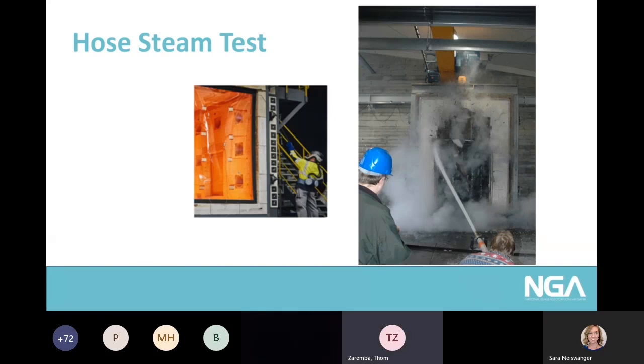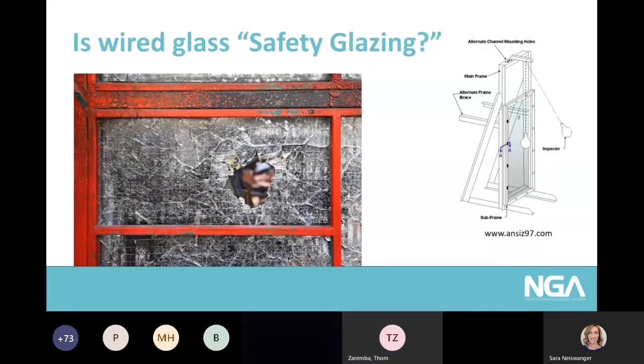Another important aspect of the use of the wire embedded in this glass is that following a 45-minute fire test, both the fire window test, NFPA 257, and the door fire test, NFPA 252, require that the glass in the door or the fire window be struck with a hose stream. And basically, there's a picture of it on the right. It resembles a fireman's hose, and it's intended to determine, after the end of the 45-minute fire test, is this product still going to remain intact when struck with the thermal shock of a hose stream? And most often, wire glass, although annealed, the wire would hold the glass together and it would survive the integrity test of a hose stream following the fire test. Next, please.